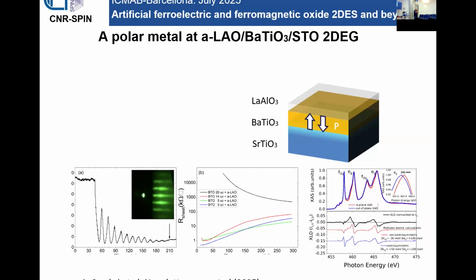Yeah, but that was actually the next question. Then the 2DEG will really form within the ferroelectric layer, right? Because the whole discussion is always about whether the electron gas is ferroelectric. It's polar, okay. One thing is to have a proximity effect, in which you have a ferroelectric layer next to the electron gas. Here, the 2D electron gas will potentially be within the ferroelectric matrix. This is the same problem we have, for example, with calcium-doped strontium titanate. So is that a proximity effect or is it really ferroelectric?